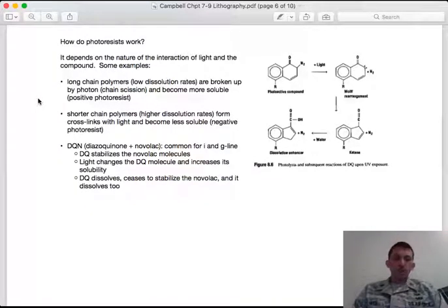beforehand. And then when you shine the UV light on them, that high energy photon can dissociate the bonds in the polymer chain, right? So you're breaking those bonds and taking long chain polymers and creating many short chain polymers. And so these short chain polymers do not have the same degree of chain entanglement.